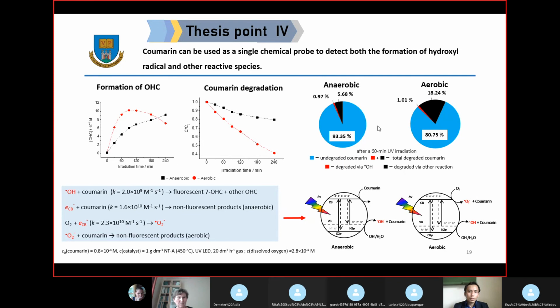The fourth thesis point is that coumarin can be used as a single chemical probe to detect both the formation of hydroxyl radicals and other active species. As I mentioned before, coumarin can react with the hydroxyl radical, producing 7-hydroxycoumarin. From this data, we can estimate the production of total hydroxycoumarin. It indicates the coumarin reaction with the hydroxyl radical. So the difference between the total coumarin degradation and the hydroxycoumarin produced indicates the coumarin reaction with other species.